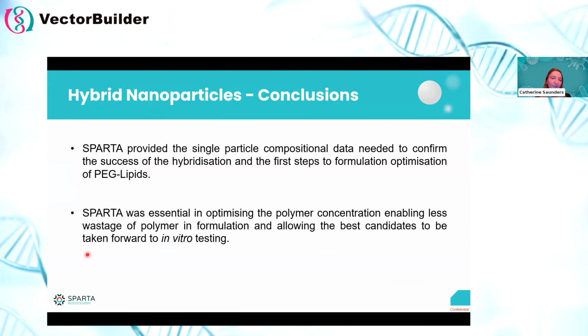So just to conclude this, SPARTA provided the single particle composition information, which was required to understand how successful this hybridization was. It also allowed the researchers to optimize their polymer concentration, ensuring that the best candidates were taken forward to the testing round and the development of the products.